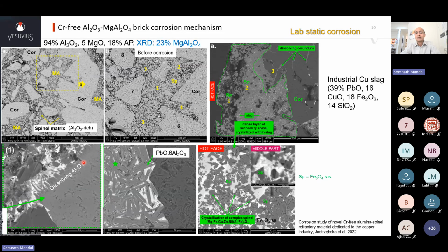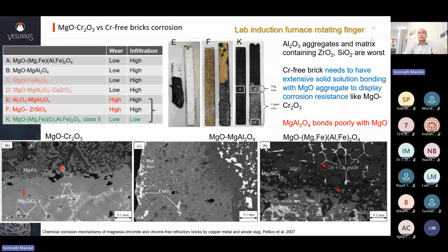Possibly like white fused alumina. So this is very bad because you don't want direct dissolution of your refractory aggregates like this. If your aggregate is dissolving like this, your matrix is going to be washed away pretty easily. And this same phenomenon was found in another study.